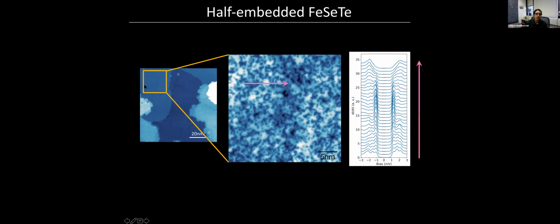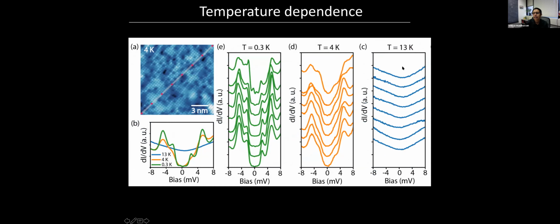Let me skip all this. So, okay, this is the FeSeTe layer. This is bismuth telluride. And if you go in here and take a series of spectra, this is what it looks like. The important thing to notice is that this gap looks exactly like the gap we saw in the bulk compound. By the way, this topography should remind you of the bulk compound. You see 3 distinct gaps, with some regions having very nice sharp coherence peaks. But the most important thing is that the density of states is actually completely zero inside the superconducting gap. So this monolayer of FeSeTe on bismuth telluride is a very, very good superconductor. And the TC is very similar to the bulk. By 13 Kelvin, that's when the gap completely disappears.